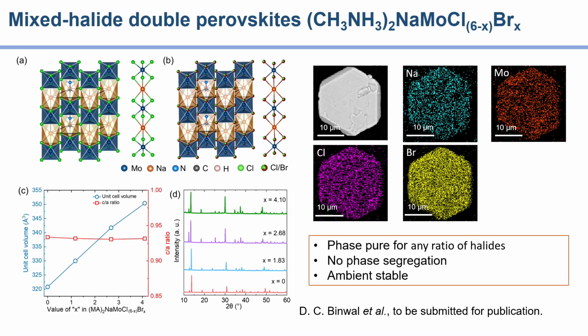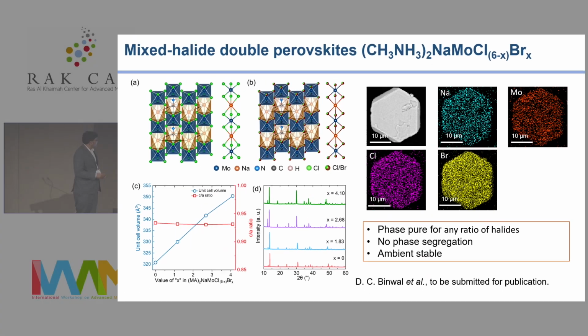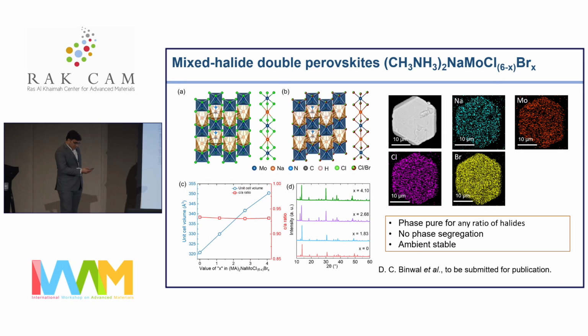So basically, these are the same structure type. We don't see a change in structure at bulk level, and of course, from single crystal it is clear that these are in the same phase, but one can increase bromide without a phase segregation, and they're very stable under ambient condition. Also, the elemental distribution suggests that there is no phase segregation. Phase segregation often is a complex situation. It creates a lot of issues, particularly in double perovskite, because there are more combinations possible, because there are ternary compounds. And then we also see, as expected, as we increase the bromide content, unit cell volume increases.